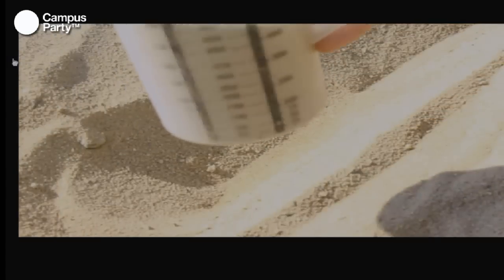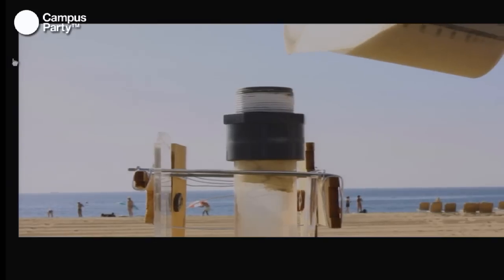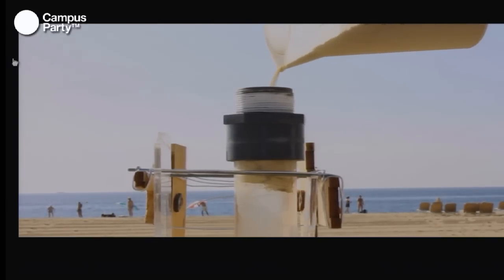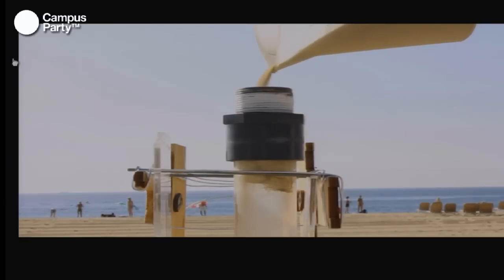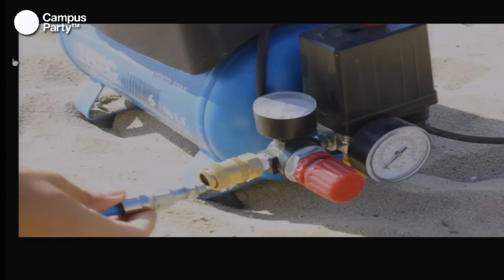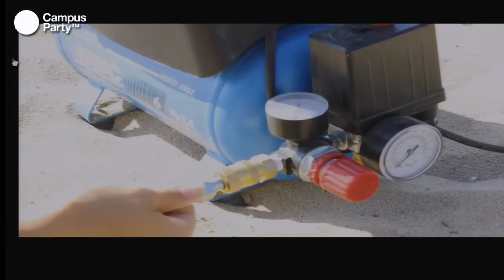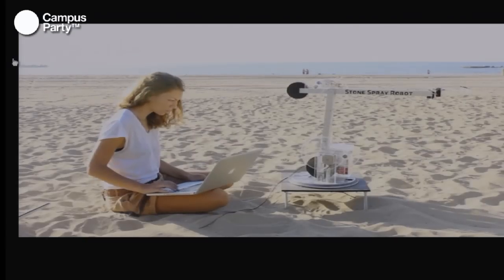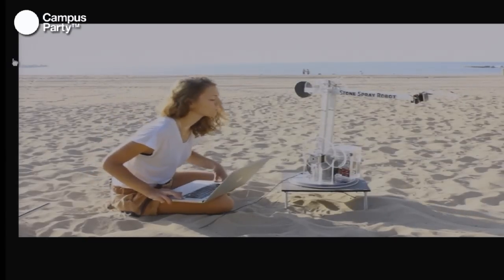As we said, you take the material just from the ground — you don't need to carry any material with you. What is also interesting about this material: you need just one liter of polymer to solidify one cubic meter of soil. So you only need to carry one little bottle to make a huge structure.